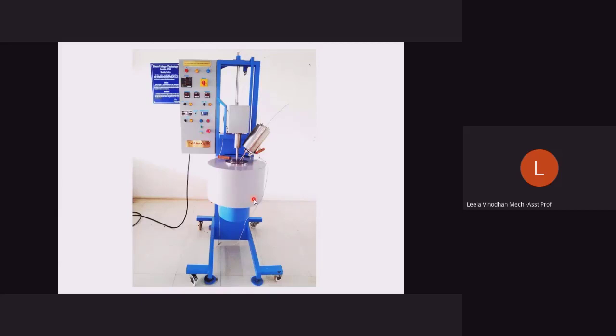As long as we have experience, the pre-treatment of the reinforcement, preheating of the reinforcement, is not only for taking out the moisture. We can still do some sort of heat treatment to the reinforcing material so that we can achieve a better result. So we have to concentrate more on that also. What we are generally using is that we will maintain some 150 degrees Celsius in order to remove the water content or moisture content in that particular reinforcement.